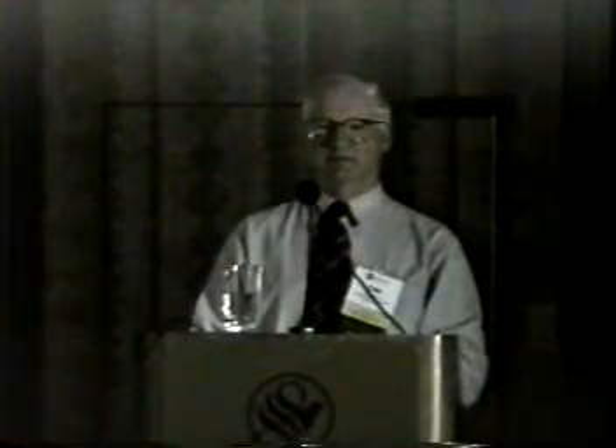Steve Bailey with Corpo. Peter, I disagree with your statement regarding product protection where you indicated that the structure could be completely destroyed as a result of discontinuous rebar. In the case of an impressed current system where you have a rectifier, if you connect the anode to the wrong terminal on the rectifier, yes, then you can accelerate the corrosion dramatically. In the case of high-strength steel, you can have problems if you exceed the voltage for hydrogen embrittlement on high-strength steel.